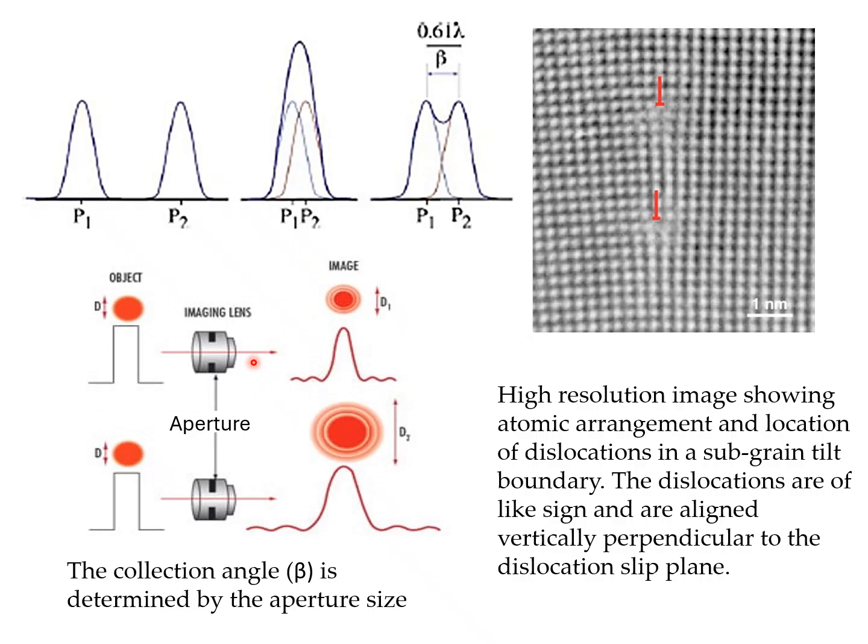So we have a large aperture, reciprocity comes into play, just as it does with Bragg diffraction, where we have this reciprocal space, where the diffraction pattern is the Fourier transform of real space. The peak width here is a Fourier transform of the aperture, and it's small when the aperture is big, and it's large when the aperture is small.